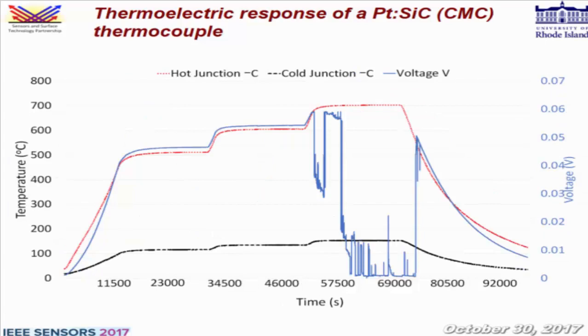So then we went ahead and tried to test at even higher temperatures. The mentality here is we're trying to go in 100-degree increments. So our goal temperature is 1000 degrees Celsius. Here we start at 500 and the sensor works. We go to 600, the sensor is fine. And then we try to go up to 700 and the sensor fails at around 660.